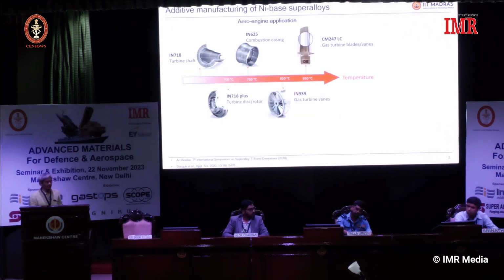To talk about additive manufacture of nickel based superalloys, traditionally they have been produced using casting or forging methods. Here I am going to discuss 3 different alloys. One is Inconel 718, which is a precipitation hardened alloy. Inconel 625 is a solid solution strengthened alloy. The other one is Inconel 939, which is used at a slightly higher temperature, 850 degrees centigrade. So the question is, can we produce them by the additive manufacturing route, and can we use them directly in the given applications, or rather, what are the traditional methods used to produce these components, and can additive manufacturing replace them?